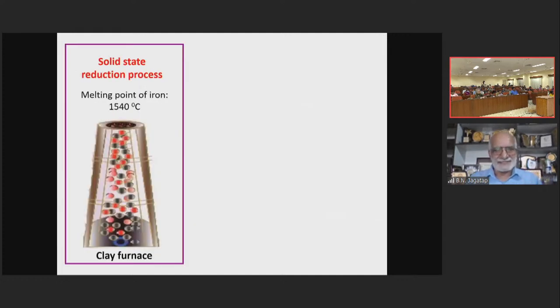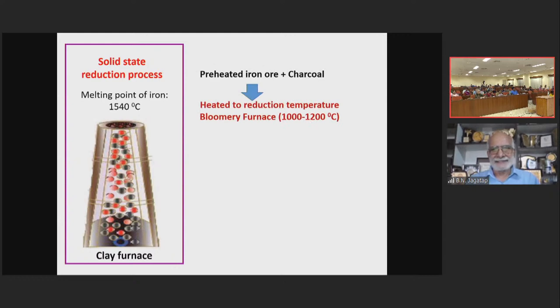Now, what is the process that these people use? It is a solid state reduction process. It's with a clay furnace, and this is where you have charcoal and the ore. Remember, the melting point of iron is 1540 degrees centigrade. Now, the charcoal gives you a temperature of 1000 to 1200 degrees centigrade. So, you have the preheated iron ore and charcoal, and this is heated in the bloomery furnace. This is the bloomery furnace. Now, this temperature is lower than the melting point of iron.